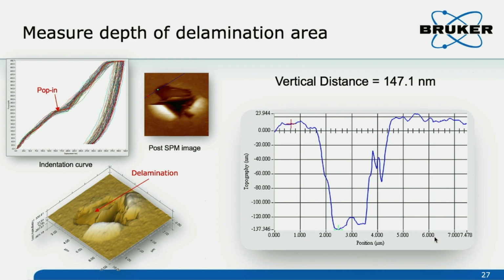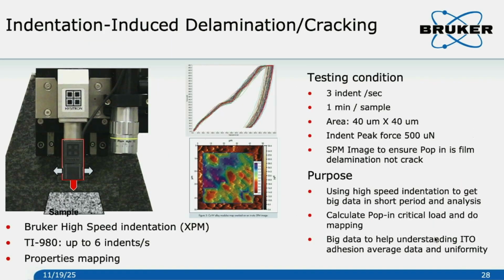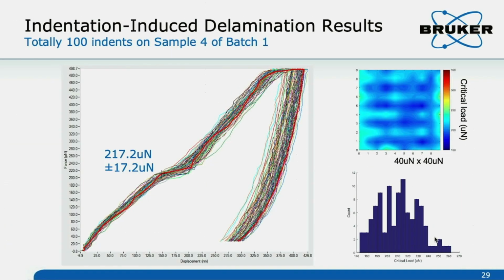And we also have the high-speed mapping, right? So we can do the high-speed mapping. This is 100 indents. You can see the pop-in is quite repeatable. So if we use the critical load here, we just pick up the start point of the pop-in, and we use the 100 indents, then we can do the critical load mapping. What does that mean? This can mean adhesion mapping.